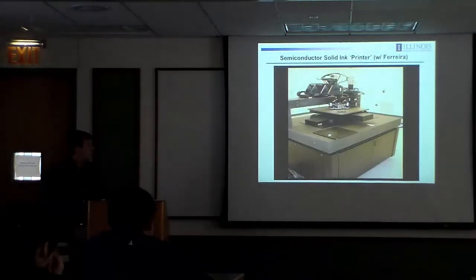And because you're doing this at room temperature, you have a lot of choices on substrate because you don't need to accommodate the growth conditions that are needed to form the materials to begin with. And so there are a lot of fundamental aspects around how you control adhesion between the stamps and these elements because you need to be strong enough to allow efficient inking, but you need to allow them to get off the stamp so you can print them down. So it really requires switchable adhesion strength on the surface of a soft material. There are a lot of ways to do that. I won't get into them now, but just say that can work.